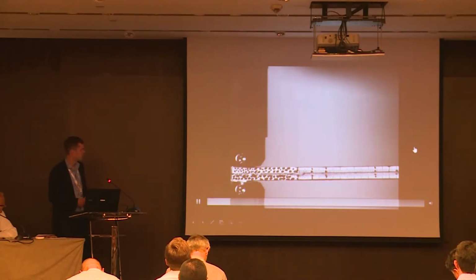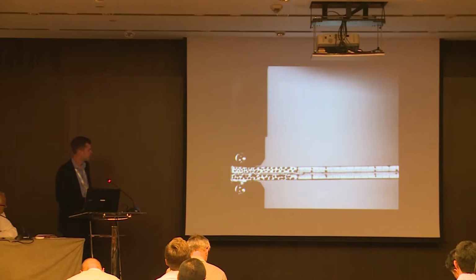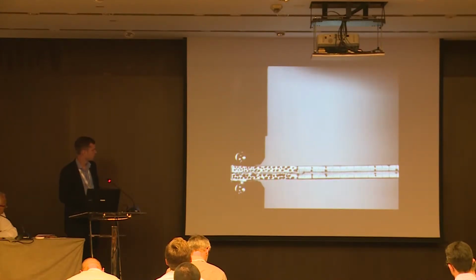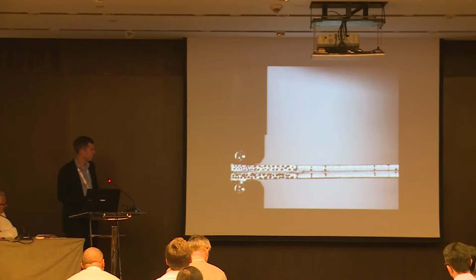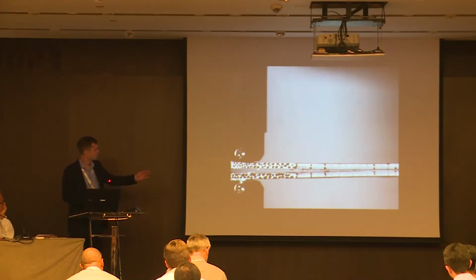You have a bar-shaped composite, and you have several marks on it, and you can determine the crack which is growing from left to right, putting forces on the left side of this bar. And by measuring forces and the crack length, you can define the fracture toughness of this material. I hope you can see this from the last row. The crack is growing from left to right.